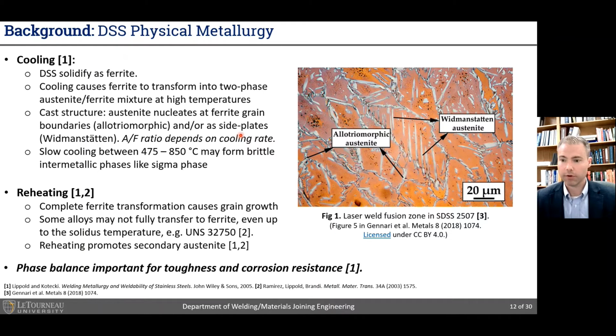So the cooling rate has a big effect on the austenite volume fraction, and slow cooling, if between 475 and 850 C, and what constitutes slow depends upon the specific composition, may promote the formation of brittle intermetallics such as sigma phase. So the time temperature history of these materials is quite important for microstructure control and property control.